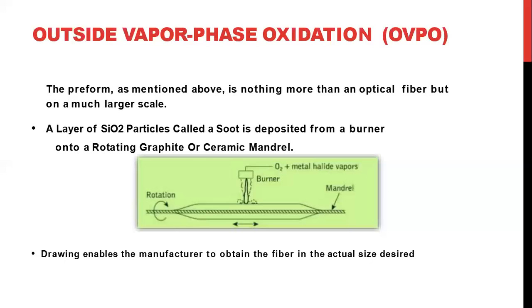So together with the material such as SiCl4, a fuel gas such as hydrogen or methane is supplied to a burner, which is again moved along the rotating rod. After the deposition, the target rod is removed and the preform is consolidated in a furnace where it is also purged with a drying gas for lowering the hydroxyl content.